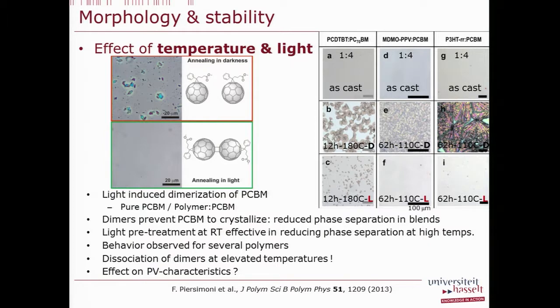You can do also light pre-treatment at room temperature. It's not only observed for MDMO-PPV, but also for various types of polymers. The only thing that we have to be careful about is now we don't have to have the feeling that everything is solved, because if you go higher in temperature, these dimers dissociate again. So if you go higher in temperature, you see that this effect is cancelled out again.